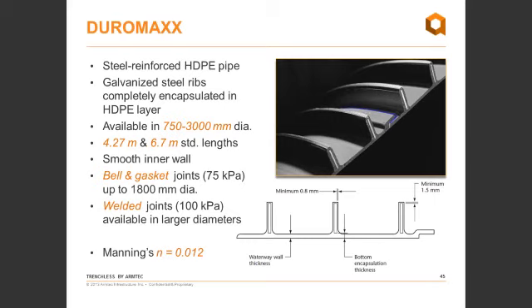So this pipe is available in diameters ranging from 750 to 3,000 millimeter. When you're thinking about a 10-foot diameter pipe, that's a nice large pipe, particularly in a plastic pipe. The one nice feature about the steel ribs is that they are quite a bit more efficient in terms of strength and stiffness than, say, an all-plastic pipe. Because when you get into larger diameters, if you're only using plastic, your only option is to put more plastic in the pipe.